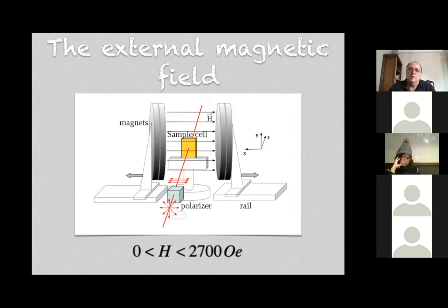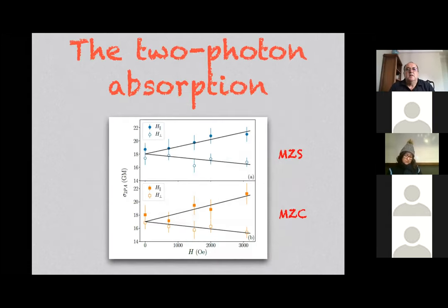But there it's not a problem because it's a fixed sample, we don't move. But in this Z-scan, we have to move this chariot with the sample along the Z direction. And this is what we measure here for the sample manganese zinc spherical particles and cubic particles here, okay? In the orientation parallel and perpendicular to the magnetic field.